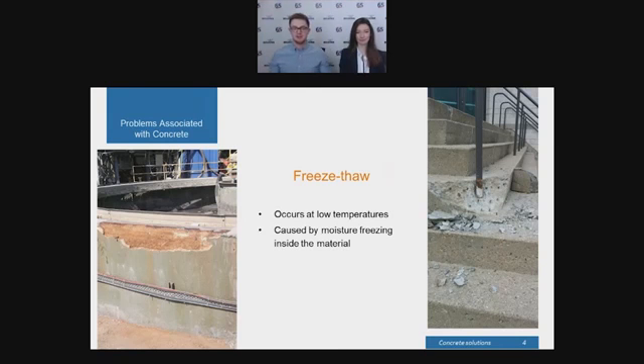So this occurs mainly at the lower end of the temperature scale. As the moisture gets inside the concrete itself, that freezes, and obviously ice takes up more volume than water. So as it freezes, it expands inside the concrete, and then it effectively pushes the concrete apart from the inside out. In most cases, this causes the damage you can see in the pictures. So the concrete can no longer hold itself together, it cracks internally, and then you get spalling of the concrete as it falls away from itself. So damage to clarifiers, steps, overhead areas, it's all the same, it's all due to moisture damage.